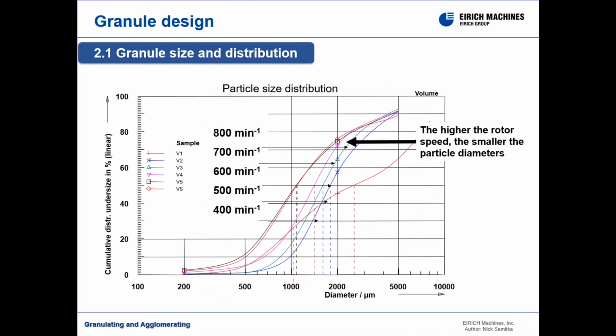This slide shows that running at higher rotor speeds or energy input will influence the particle growth and tighten the distribution curve. So starting at 400 RPM, when we increase the speed up to 800 RPM, the distribution gets much tighter.